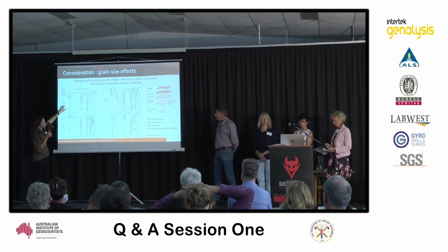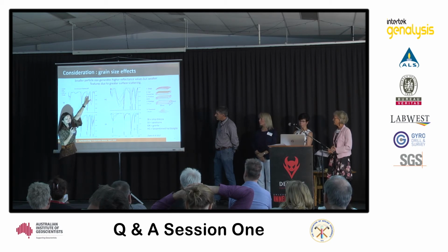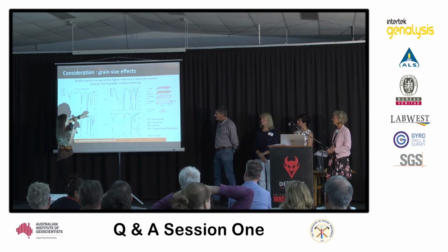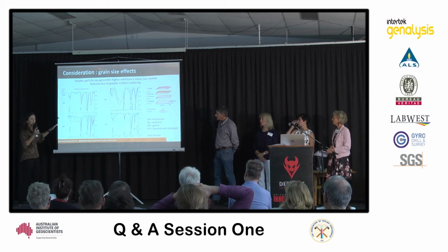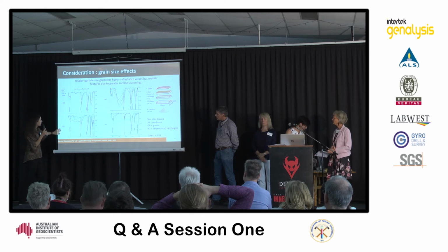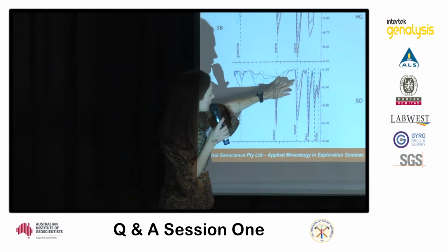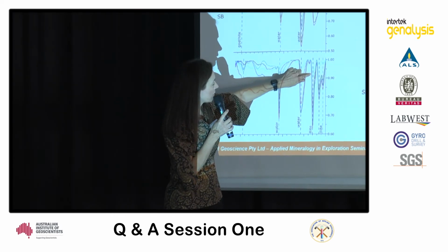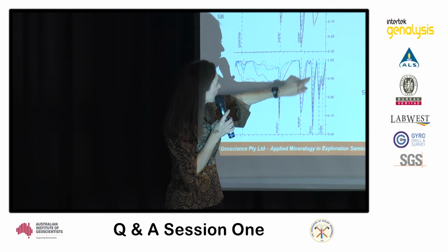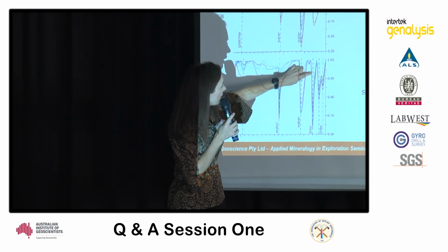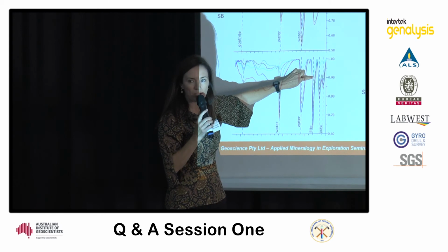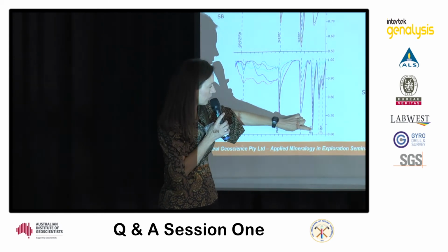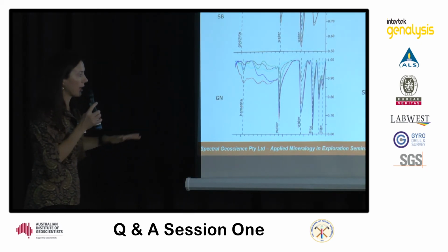Just for, say, the silica breccia up here, you can see the size difference between the absorption features. It's quite shallow when it's a powder compared to when it's just the slabbed core. Similar for the granite, and it's these absorption features, say, when you're looking at the illite 2200 feature, it's really quite shallow for the powder compared to just the drilled or the cut surface.